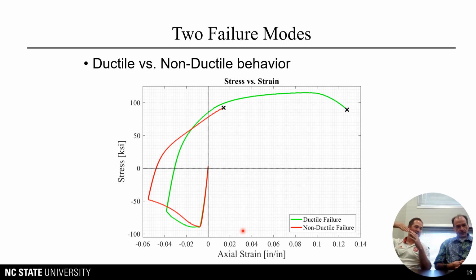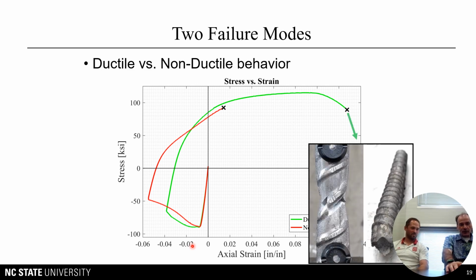So the green is obviously not subjected to as much. It does buckle, because the force doesn't continue to increase as the bar buckles. But it hasn't buckled to such an extreme level that when the loading was reversed, the green bar could fail in a ductile manner. Like you saw on the previous slide, there you experienced necking. Subjected to just slightly higher curvature, the red, we saw a brittle fracture. So that distinction tells us that the critical bending strain is somewhere between those two values.